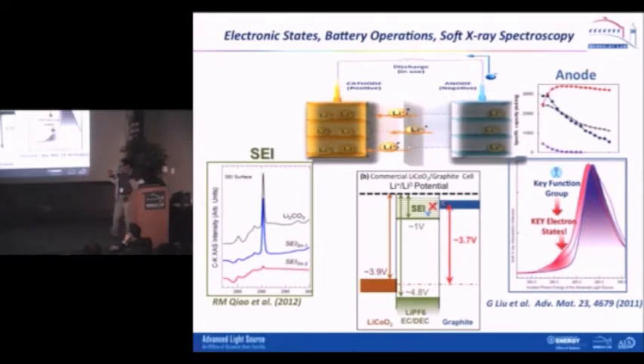The soft X-ray really could tell you many aspects of all this information. So this is an SEI sample we detected using soft X-ray absorption by Ruimin Qiao in our group. On two anode surfaces, these two surfaces have very different performance. The red color surface has a very stable cycling performance, while the blue one is very bad. Using soft X-ray spectroscopy, what you can see is that on one of the surfaces, you form from the beginning a pretty okay surface layer, while for the other one, the electrode itself has a catalytic type of performance to decompose this SEI layer and form another type of SEI.